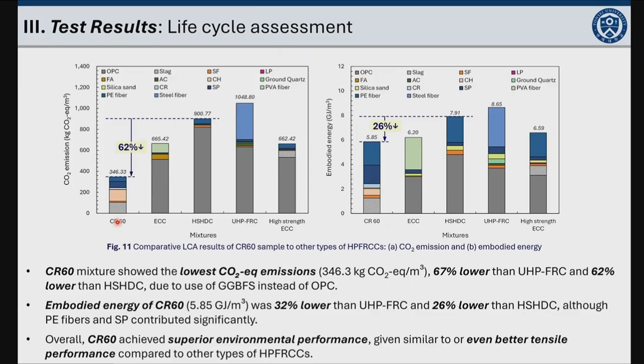The embodied energy of the CR60 mixture was also 32% lower than UHPFRC and 26% lower than high strength and high ductility concrete. Therefore, it can be concluded that the developed composite achieved superior environmental performance given similar to or even better tensile behavior as compared to other types of HPFRCCs.